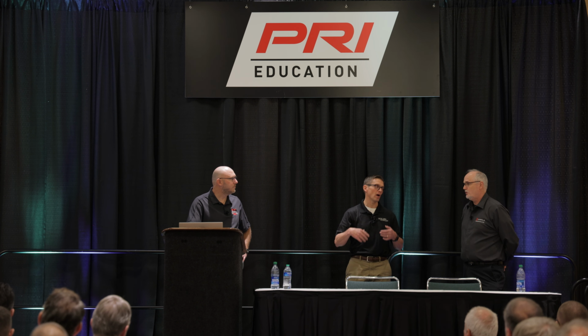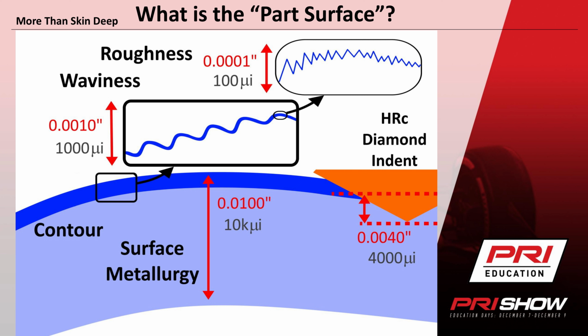So I kind of did this up so you could get an idea of the scales of the three things. If you imagine that dark and light blue line, that's the surface of your part. And you can see that the surface texture and everything is up there on that dark blue line. You can see that's broken up into the waviness and roughness. But then you've got the compressive stresses you might have left over from nitriding or shot peening, and those could go up to about 10 thousandths deep. But really most of it's in the first 5 thousandths.